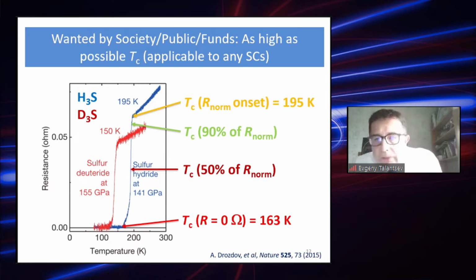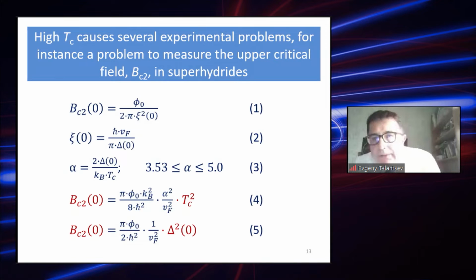There are many problems associated with these new hydrogen-rich compounds, but another problem I want to point out is that we do not have many experimental tools to study them. For example, we cannot measure the upper critical field. Why is that? If we use BCS theory and Ginzburg-Landau theory and simply substitute all values, we find that the upper critical field is proportional to the transition temperature squared. This means that if we compare these new superconductors with A15 superconductors, which have a transition temperature of nearly 20 Kelvin, and the new ones above 200, we should expect a difference in upper critical field of 100 times,